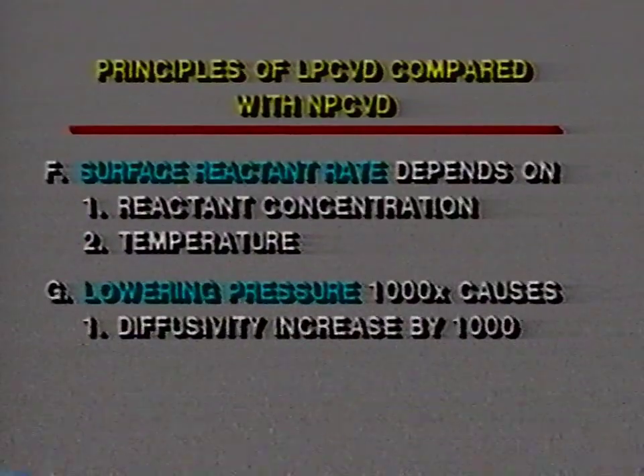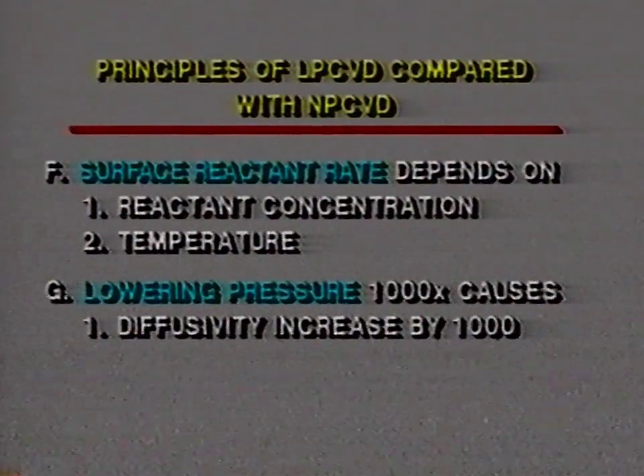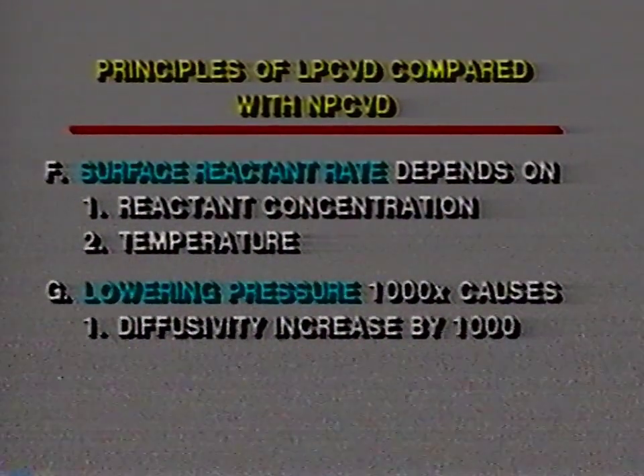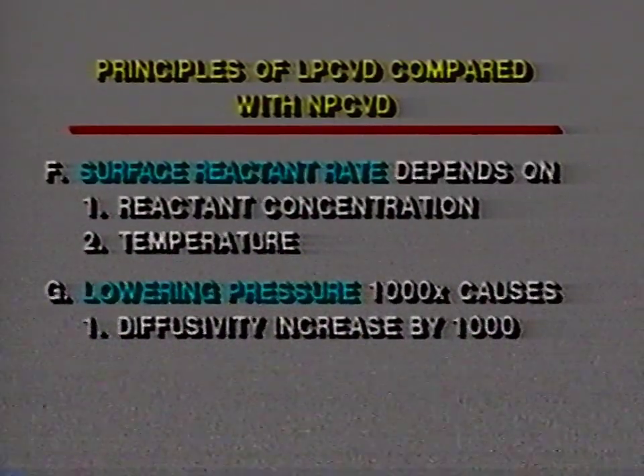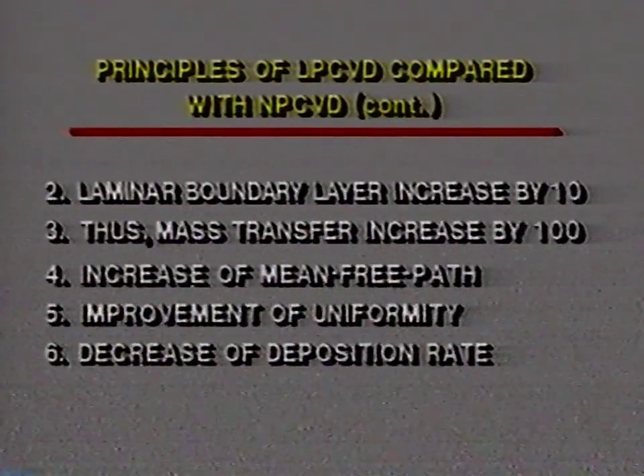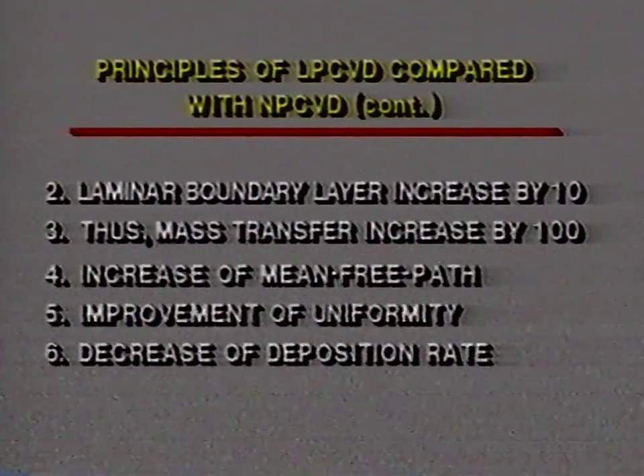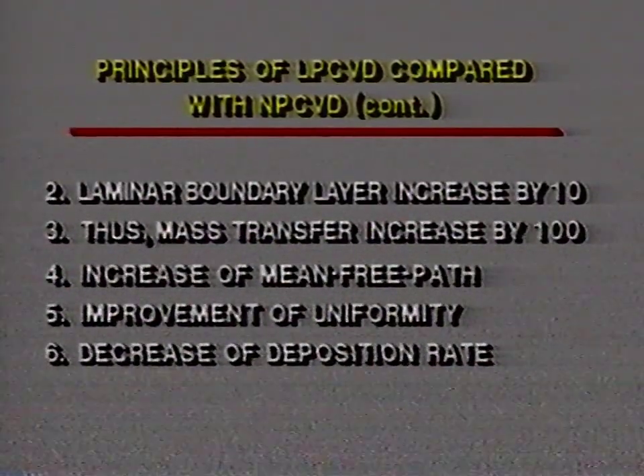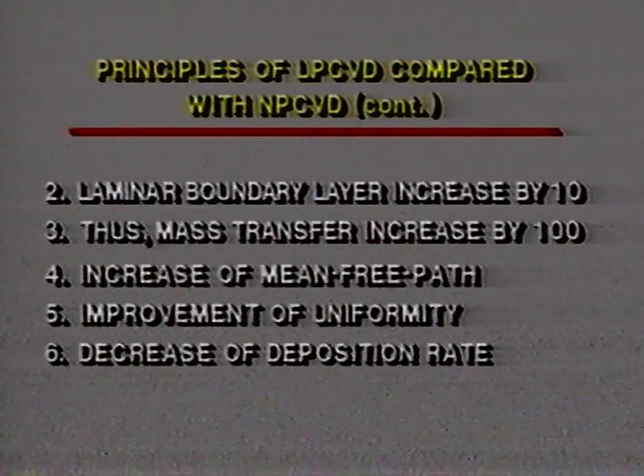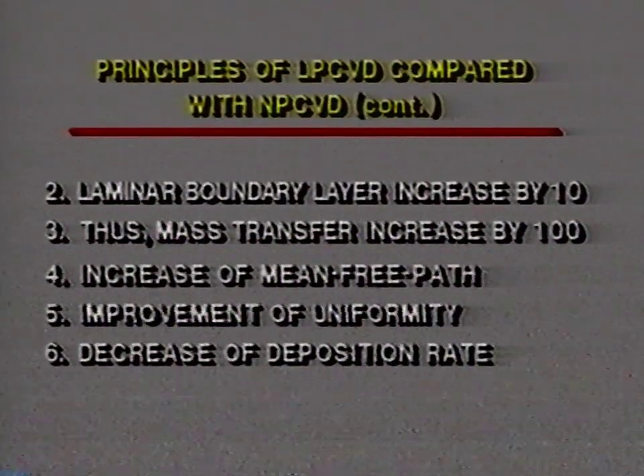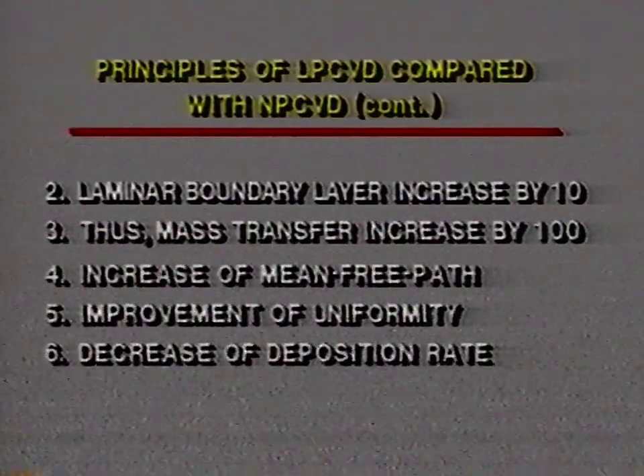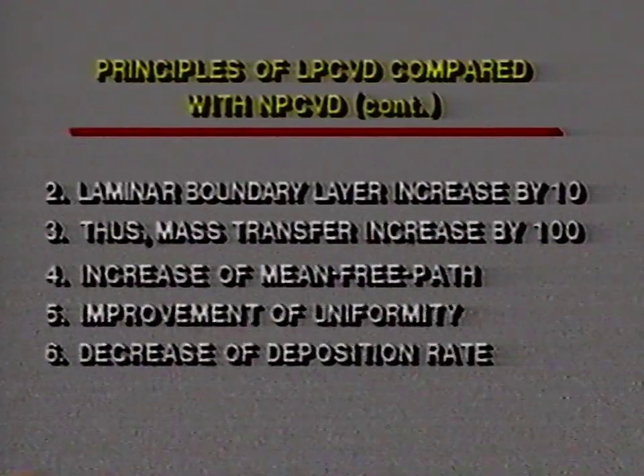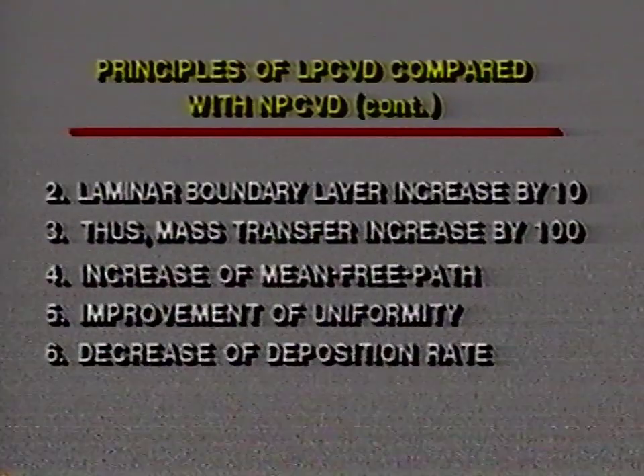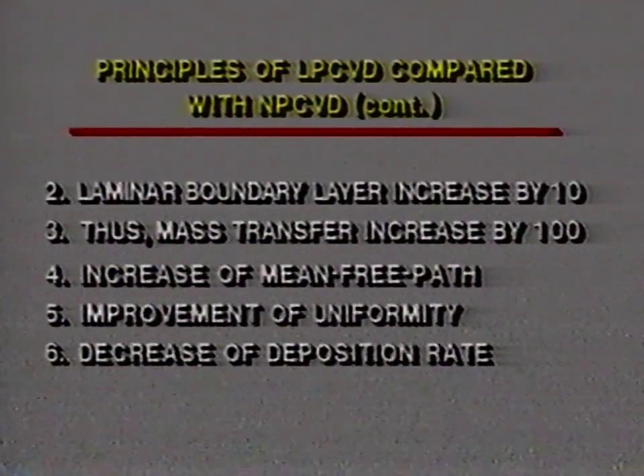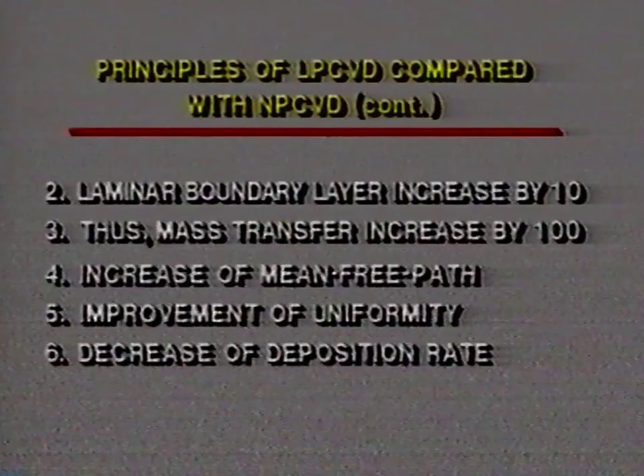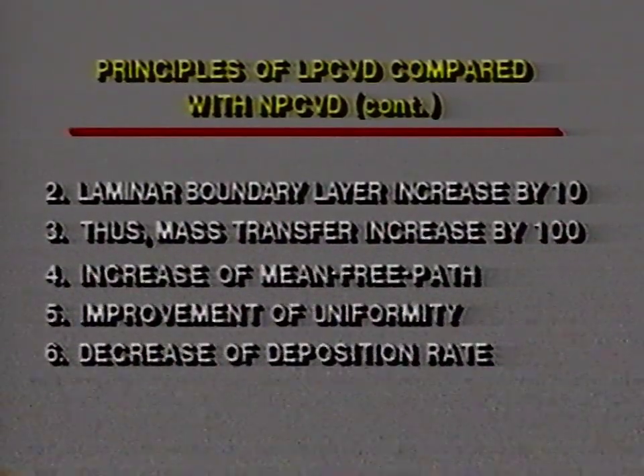Now, if you lower the pressure by a factor of 1,000, let's say from atmospheric 760, what happens is the diffusivity increases by 1,000, and as a second consequence, the laminar boundary layer increases by a factor of 10, and the mass transfer therefore increases by a factor of 100 because of these factors. Of course, the mean free path is increased as a result, and as a result of all this, the uniformity of the film deposit is greatly increased.